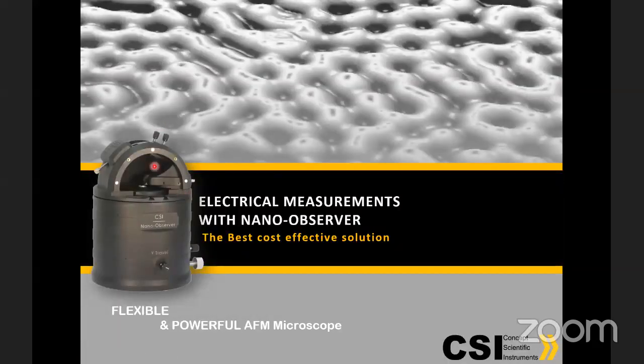Yeah, so this is the environment that you want to focus on. In our case, for example, here's the tip and here's the sample. And that is why we've cleverly, in a certain sense, designed it so that it is housed in almost a semi-closed enclosure itself. So what I need to worry about to make a clean measurement is the cleanliness between the tip and the sample region. Often the way we control this, especially for electronic and magnetic measurements, is that we normally have another hood that closes this space out, and then this environment becomes hermetically sealed. And then we slowly purge an inert gas,